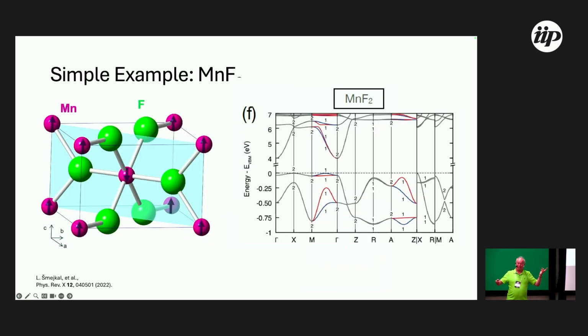One of the examples that they come up with is manganese fluoride, which, heck, that's what Sergio Rezende worked on like five decades ago. And indeed, it has a spin-polarized band structure. Now, for transport, it really doesn't matter because it's an insulator. All the spin polarization is at states where we really don't care.